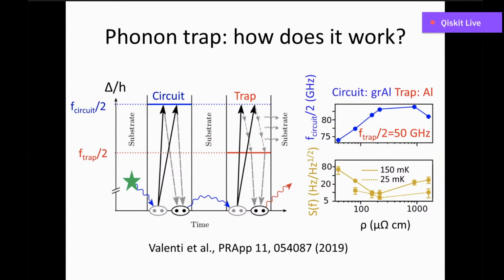I can make my circuit with granular aluminum and my trap with aluminum, as I mentioned before. And as I mentioned before, we can make several circuits by sweeping the gap of granular aluminum by making it with a different resistivity. It will follow the dome shape that I've shown before. And if we then look at the noise spectral density of the resonators, we will see that the noise is anti-correlated with the superconducting gap of granular aluminum. Or better yet, it is anti-correlated with the difference between the gap of granular aluminum, which is the circuit, and the gap of aluminum, which is the trap.